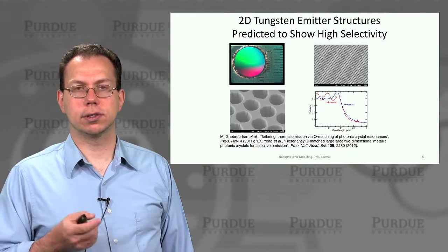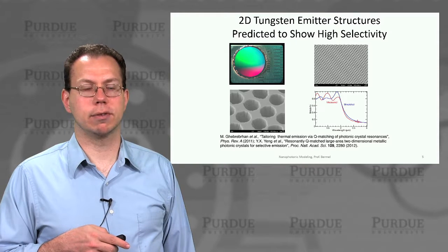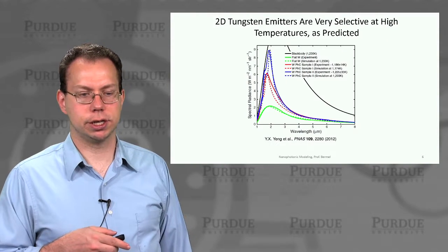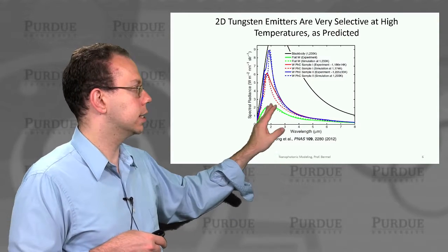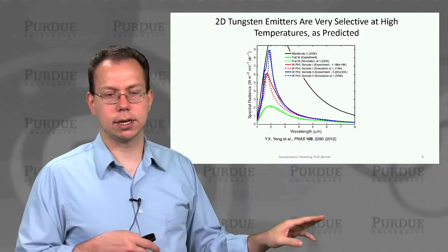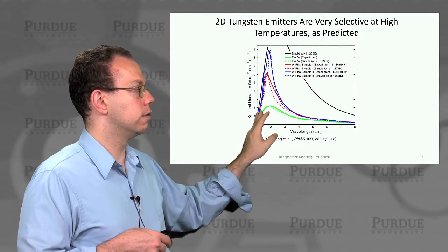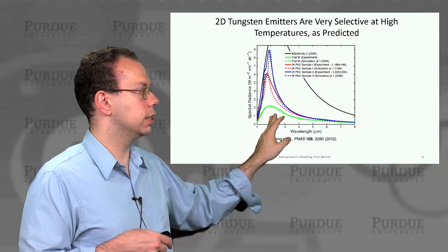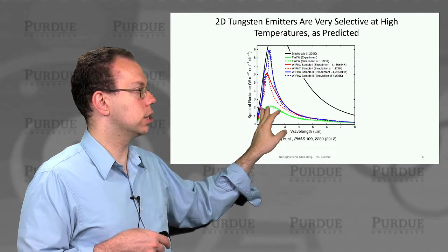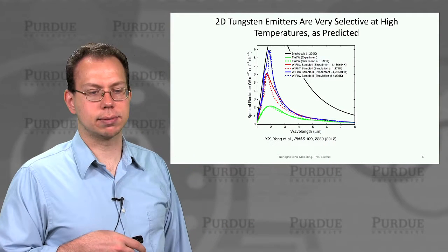And so of course, once we had the room temperature pictures and measurements, we wanted to drive this up to high temperatures. What we see is that, first of all, if you just had flat tungsten as a control, it looks like this at a temperature of around 1233 Kelvin. And the dotted line is just showing the simulation. So you have a good match to our simulated expectations.